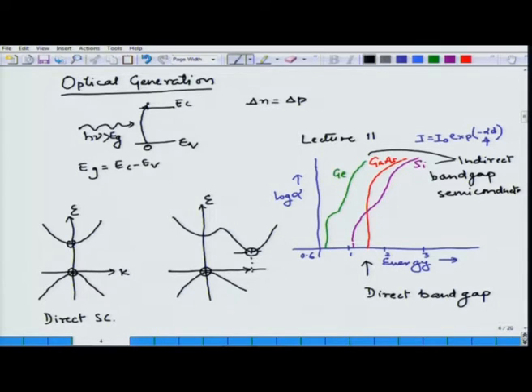I will just briefly say what happens here is that when I shine light of a wavelength equivalent to energy which is higher than the band gap, then I am able to excite an electron across the band gap to the conduction band, thereby immediately absorbing that. In this process of absorbing the light, the electron's crystal momentum does not change, and it can absorb the light and go to the conduction band. And the process is very efficient, and hence gallium arsenide has a very large absorption coefficient.